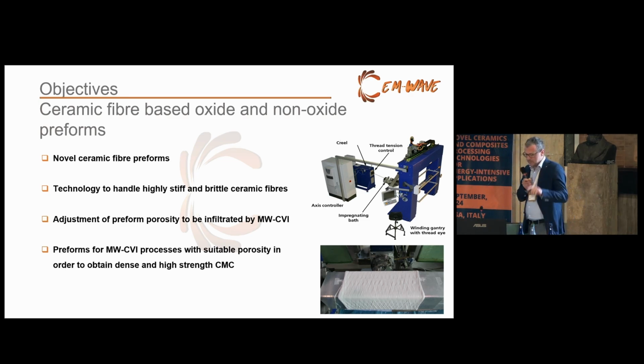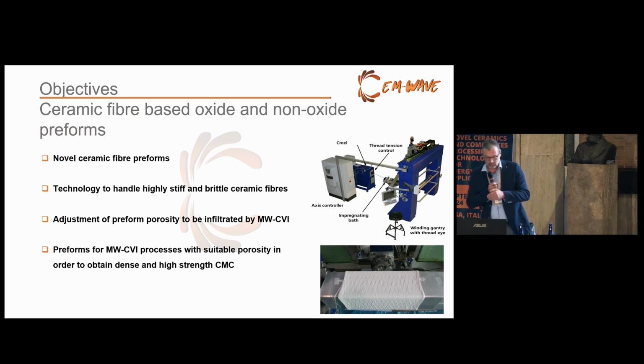Normally we used round tube cores to produce the preform material, both silicon carbide fiber reinforced silicon carbide preforms, and aluminum oxide preforms. And this is a nice thing that you can use one technique for completely different ceramic fiber reinforced materials. Of course, with the preforms using the winding technique, you have a small possibility to get some material parameters shift, of course, to lower porosity or to higher porosity.